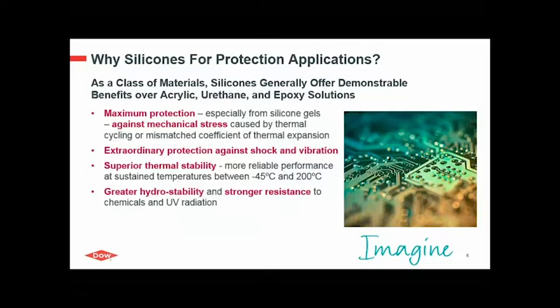As a class of materials, silicones generally offer demonstrable benefits over organic solutions like acrylics, urethanes, or epoxies. They provide maximum protection against mechanical stresses caused by thermal cycling or CTE mismatch, especially when using a silicone gel. Due to their low modulus and high elasticity, they also provide extraordinary protection against shock and vibration. Silicones are also well known for their thermal stability, providing reliable performance at sustained temperatures generally between minus 45 and 200 degrees Celsius, with potential to extend in both directions.